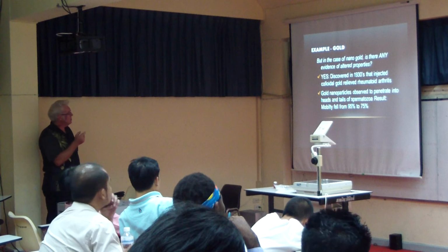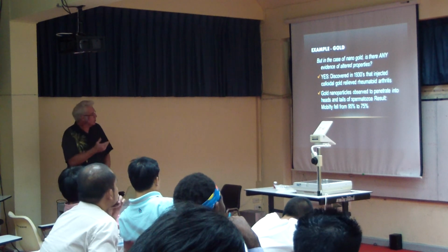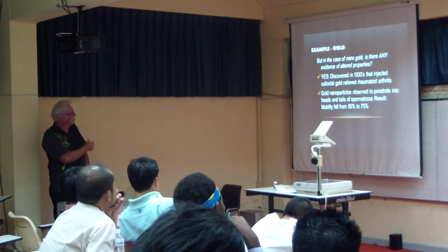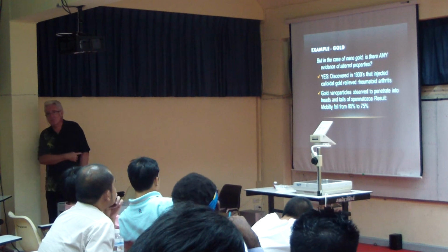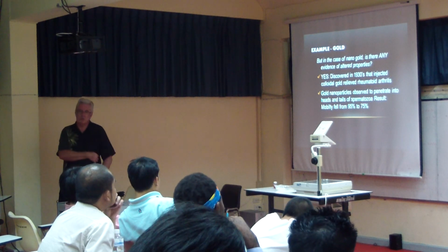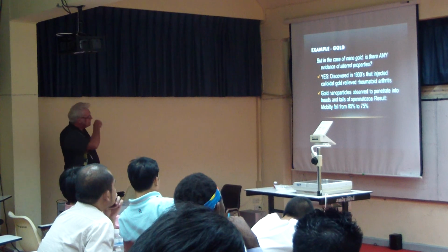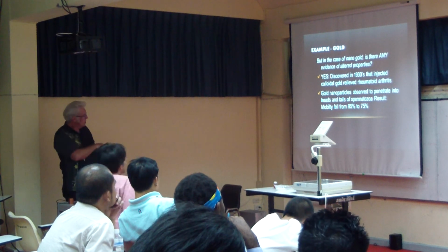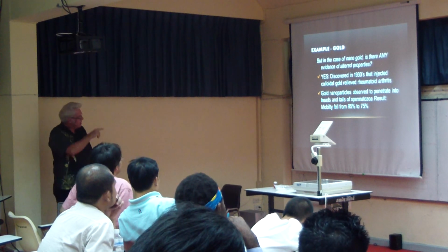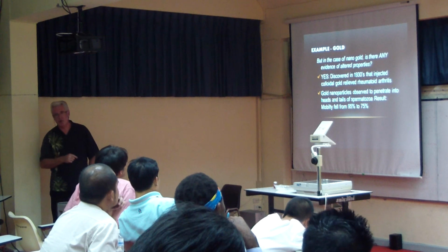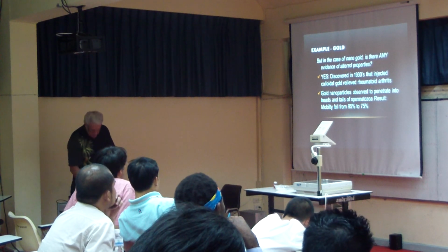An example, people have injected colloidal gold into their joints since the 30s for rheumatoid arthritis. It's supposed to help rheumatoid arthritis. However, it's been shown that the mobility of spermatozoa decreases in the presence of gold, with these gold nanoparticles.